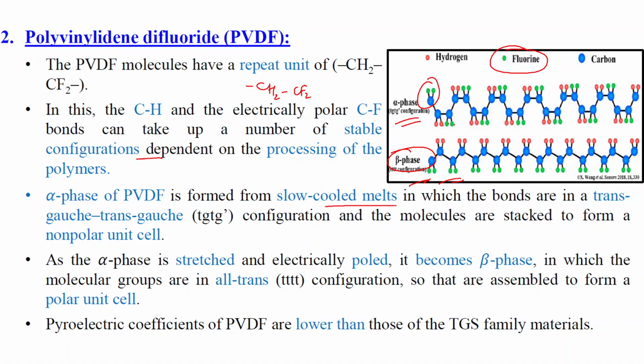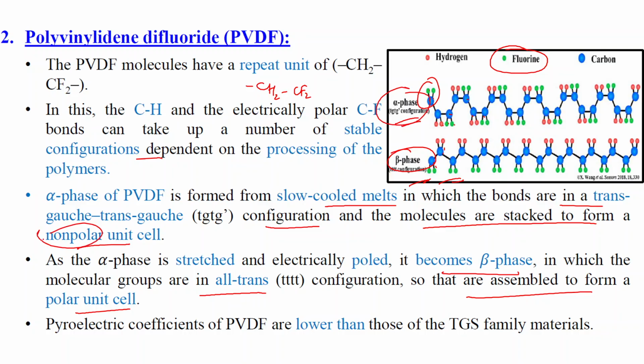So the alpha phase of PVDF is formed from slow cooled melts in which the bonds are in a trans-gauche, trans-gauche configuration, and the molecules are stacked to form a non-polar unit cell. Whereas when the alpha phase is stretched and electrically poled, it becomes the beta phase, in which the molecular groups are all in trans configuration. They are all in trans state, whereas here they are in trans-gauche state. So they are assembled to form a polar unit. In the alpha phase, it is non-polar due to trans-gauche configuration, whereas in the beta phase, due to all-trans configuration, it is a polar unit. So we need polarity basically. That's why the beta phase is mostly used in fabrication of PyNGs.